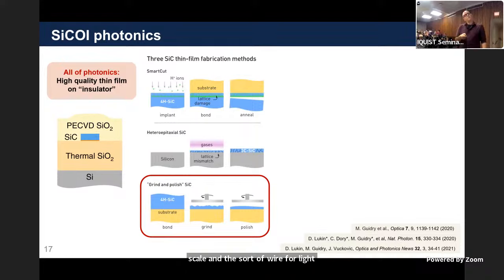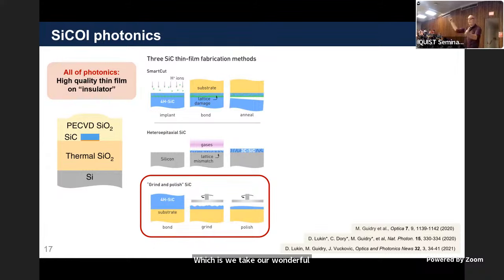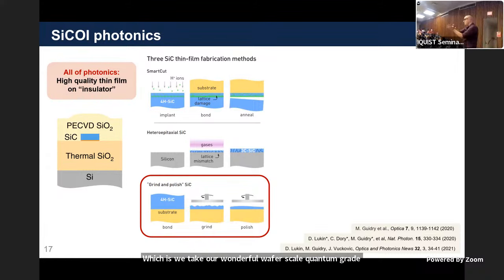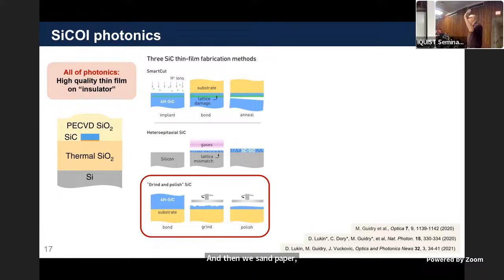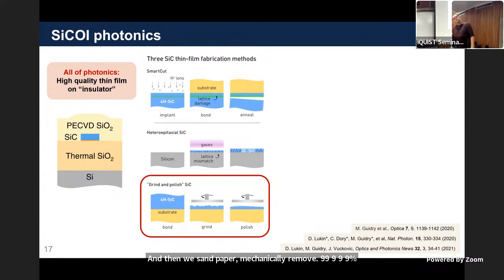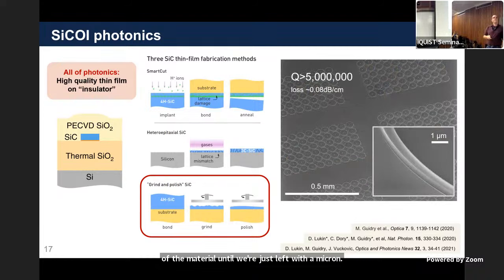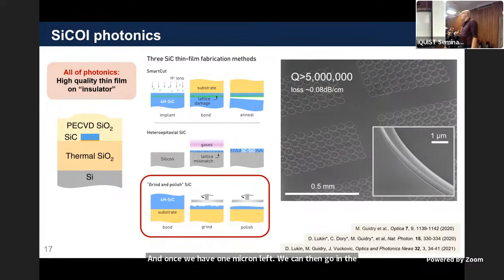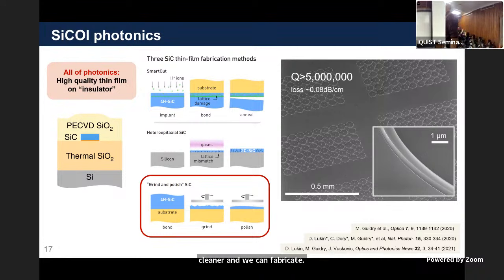In practice, we make these films, although there are many ways, using the simplest possible thing you can maybe think of, which is we take our wonderful wafer scale quantum grade silicon carbide, we bond it to glass, SiO2, and then we sandpaper, mechanically remove 99.999% of the material until we're just left with a micron. Once we have one micron left, we can then go in the clean room and fabricate wonderful optical resonators at the nanoscale that also have high quality factor.